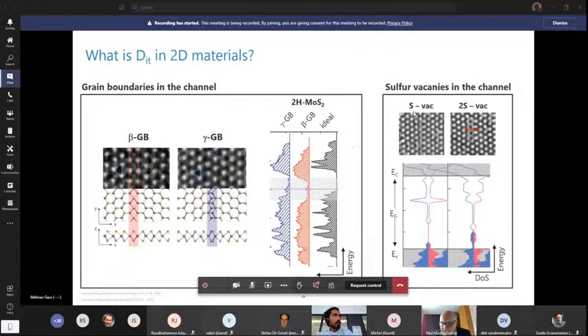This paper is not our result. It's from another group that makes CVD MoS2, and they find that the sulfur vacancies, even though you have very large grains, are still dominant. So you see how that will affect the changing of the defect location, right? Yes, and seeing an upper band gap DIT, as you observe experimentally. Yes.